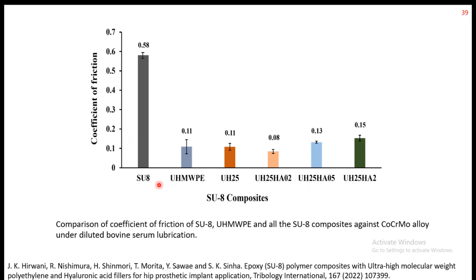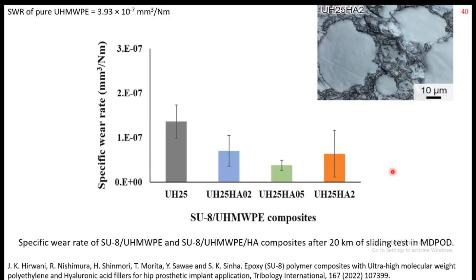In terms of wear, another important factor, we measured the average coefficient of friction in the steady state, and it gives a low coefficient of friction for our composites, even compared to pure UHMWPE. This is very encouraging.